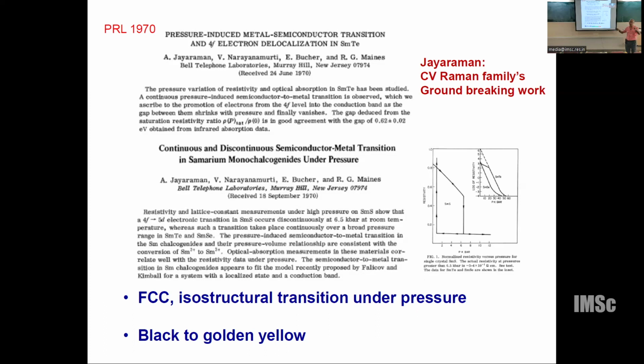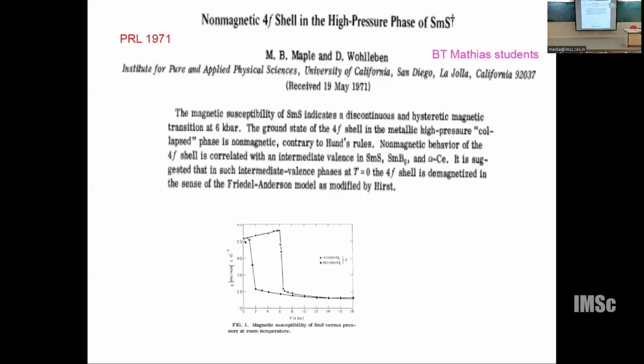So in other words, the magnetic behavior looks somewhat intermediate between 2 plus and 3 plus. At high temperature it looks like a localized moment, and at low temperature it appears there is no magnetism. It is very funny. This was not understood, but for the first time, this group of people, Maple and Wohlleben, came out with an interpretation for these anomalies: a sudden change in volume, a sudden change in properties, lattice constants not matching what you expect for complete transformation, and an intermediate magnetic behavior. At high temperature you have magnetism, at low temperature you don't. How do you reconcile all these things?